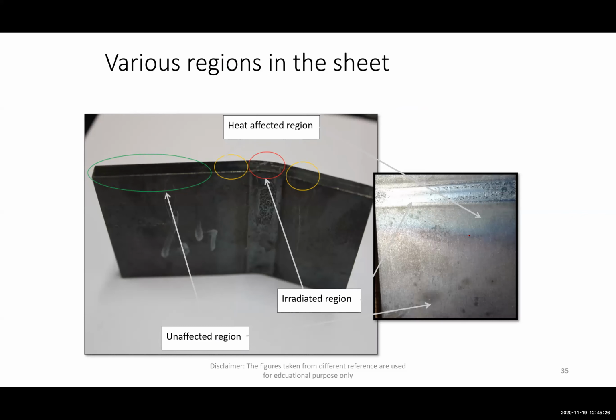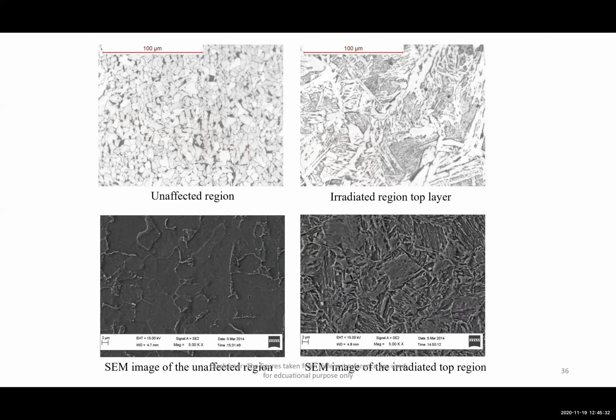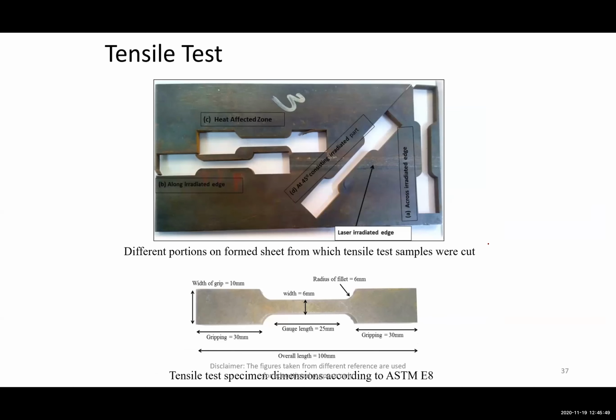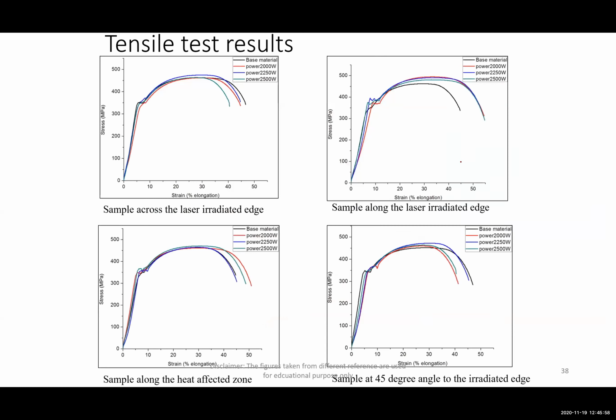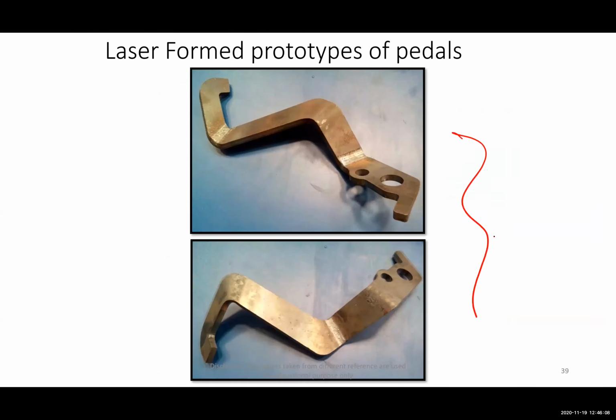So we almost restricted our application towards the prototype based system. With respect to a prototype based system, since we are going for a detailed analysis, we went for scanning electron microscopy. So basically, this is an unaffected region, this is an irradiated region, and this is an unaffected region, and this is an irradiated region at the top. We also went for complete mechanical testing. As far as mechanical testing is concerned, we went for tensile testing where we made tensile testing samples at different points, and then we went for a complete mechanical analysis. With respect to the mechanical analysis, we could almost segregate how much the mechanical property is getting improved. So these are the laser formed samples which we have done for the industry.